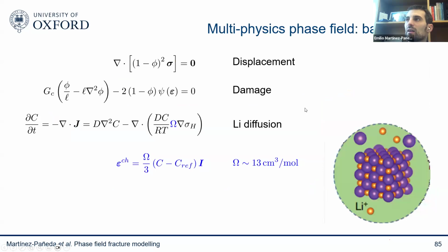And the models are relatively simple. So again, you solve a displacement problem and a damage problem. But now, in addition, you solve a lithium transfer problem. This is an extension of Fick's law, where you can see it's strongly coupled with mechanics. So you solve for the concentration of lithium ions in time. And this depends on the hydrostatic stresses. And this also brings some chemical strains. This is this lithiation process. You intercalate lithium there, and that change in concentration brings some chemical strains that rely on the partial molar volume. And those chemical strains are what bring the cracks.